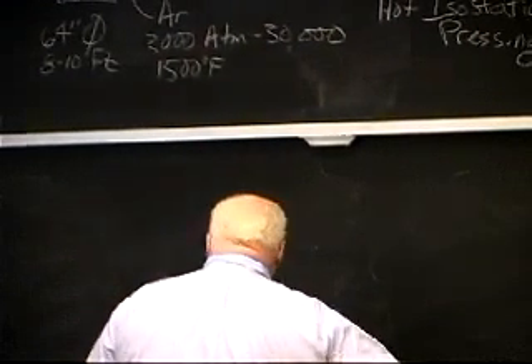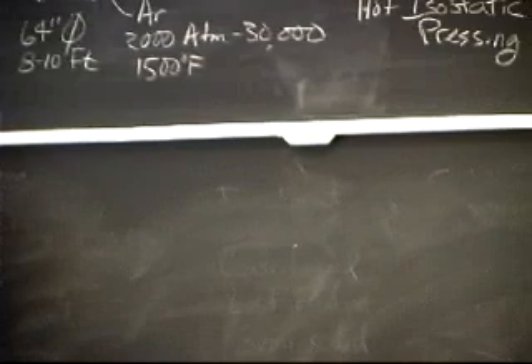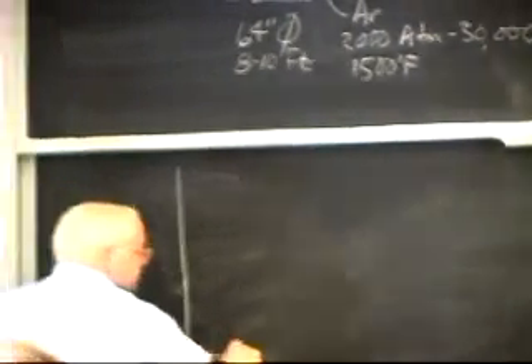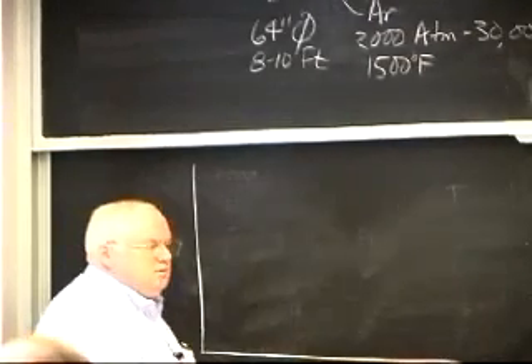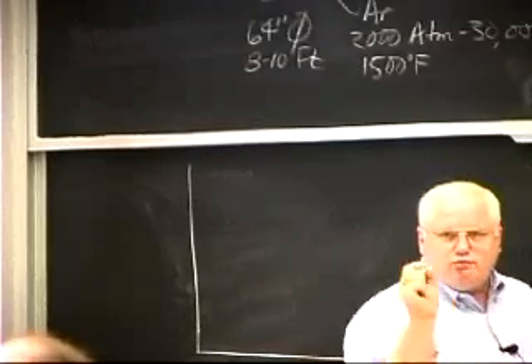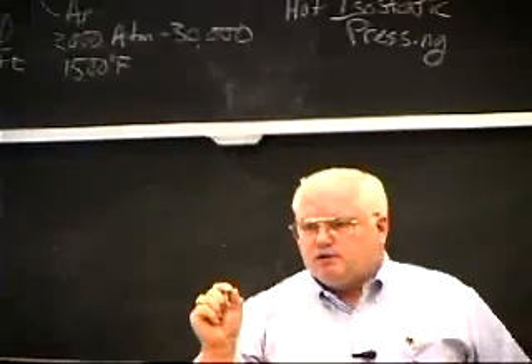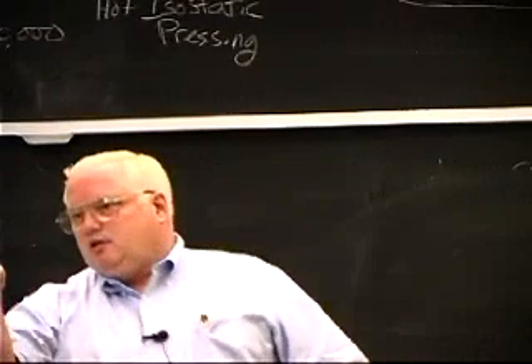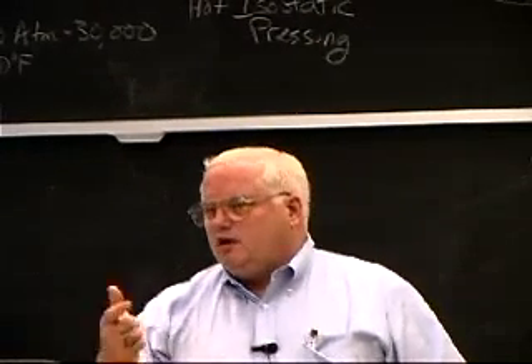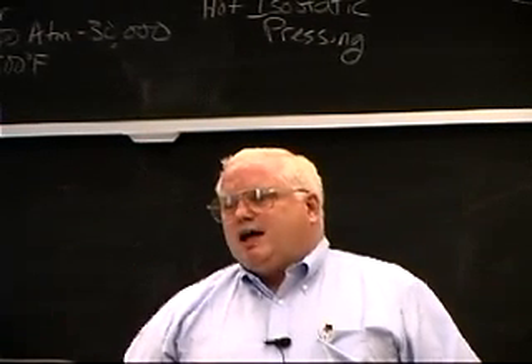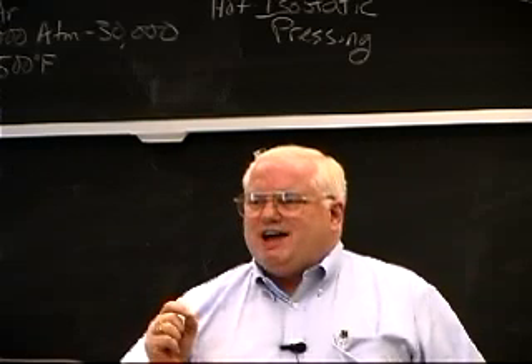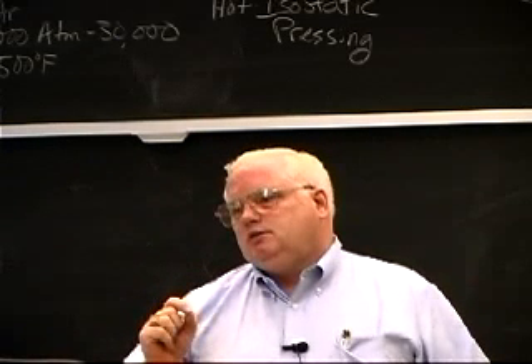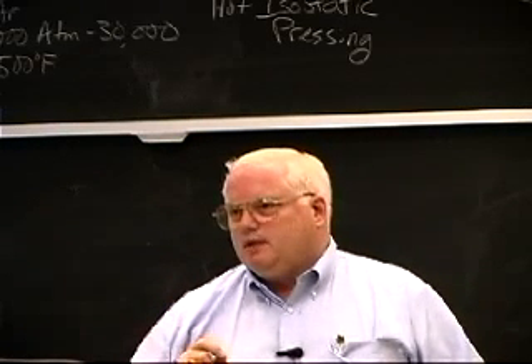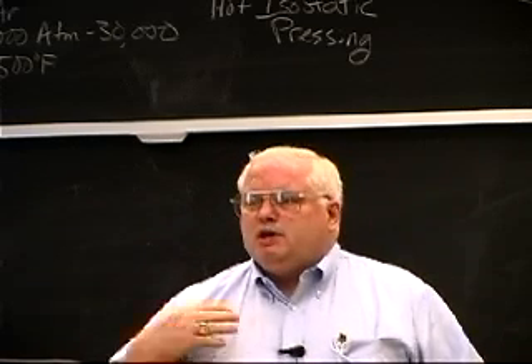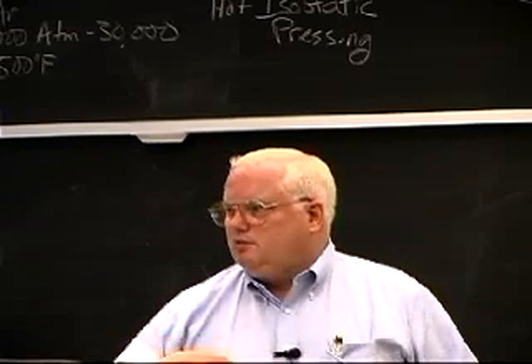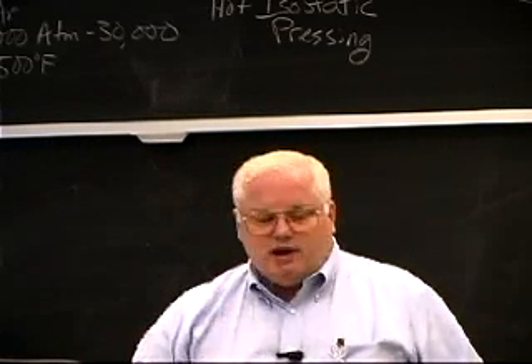I mentioned that the main thing, the thing that every metallurgist would like to do, is get finer grain size, smaller grains in the product. In fact, that little piece of copper back there that we passed around once before has very large grains. It turns out that's got about 0.1% silver in that particular alloy, which makes it more resistant to grain growth, although not in the straight cast form.